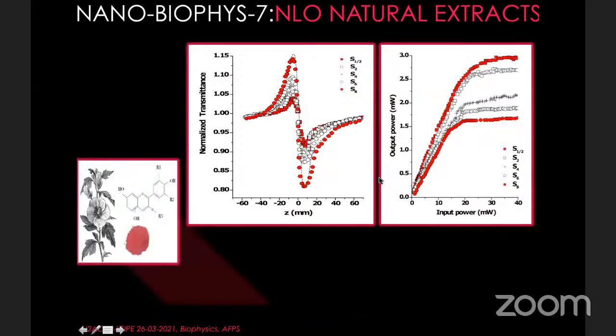He has been able to show that it has an optical limiting behavior. For those who are not expert in the field, this means that for low intensities, the transmission of that dye will be linear, but when the intensity of the laser reaches a certain value, it saturates. It does not transmit higher values at all. And the same thing for other high concentrations. This is what we call optical limiting.